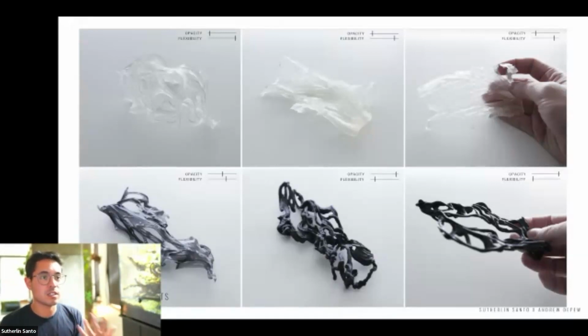Part of the reason is that while it's hot and while it's been congealing, it's reformulating, reattaching all those molecules into a new kind of biopolymer strand. Once you cool it, it becomes jello-like because everything is becoming more static, which means no new molecules are connecting anymore. So ideally, you do all the mixing and blending you need to do while it's fairly warm after it comes out, so that everything is still free moving. And once it's blended with your granules or your fibers, the molecules can still reattach to some degree while it's still free moving.